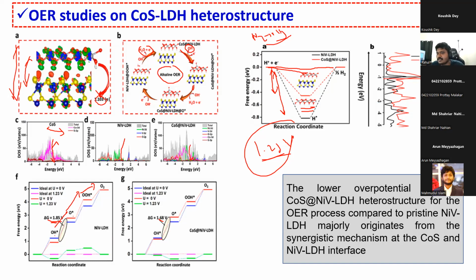Again, we come to the concept of d band center. As I previously told, this is the Fermi level. If the d band center is very close to the Fermi level, it has good adsorption characteristics. Now, for the hydrogen adsorption, if you consider a catalyst and put hydrogen on it, if the hydrogen gets adsorbed very strongly to the substrate, then we cannot take the hydrogen back. If you see the reaction steps here, hydrogen comes and sits on the substrate, then we have to convert that into H2. So basically hydrogen should adsorb, then it should desorb from the substrate. If the hydrogen binding energy with the substrate is very strong, then we cannot take the hydrogen back. So for the HER, you should keep in mind that it should have a moderate adsorption.